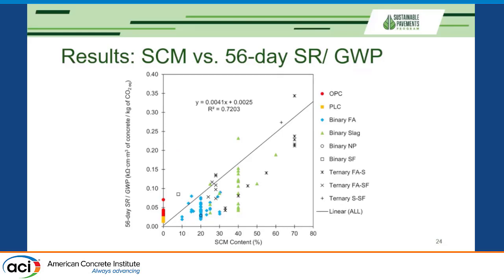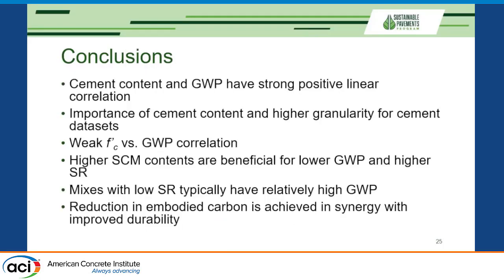Very similar trend here for the composite parameter, that's surface resistivity over GWP, meaning how much are you polluting to create a unit of resistivity. Again, with SCM content, this number is increasing, and we can see our better performing mixes all are doing pretty well. They all have higher SCM content, and generally speaking, have a higher value of this parameter. That's kind of what characterizes them as better.